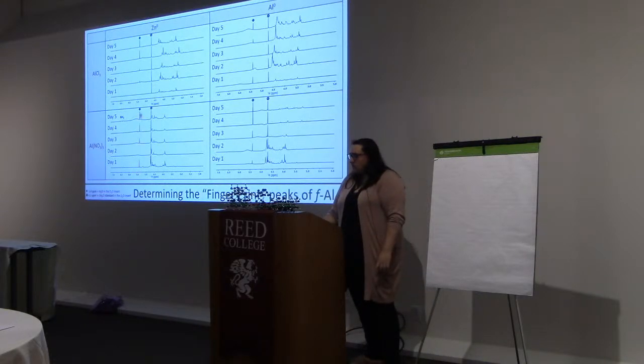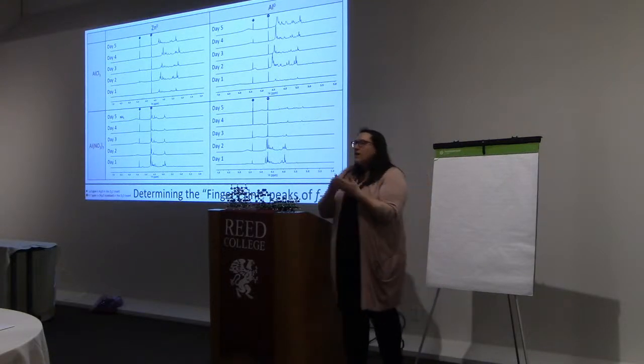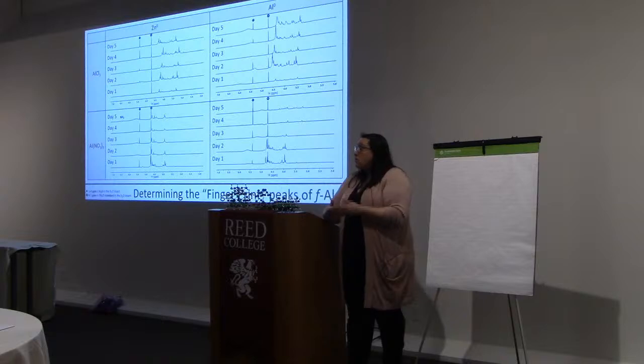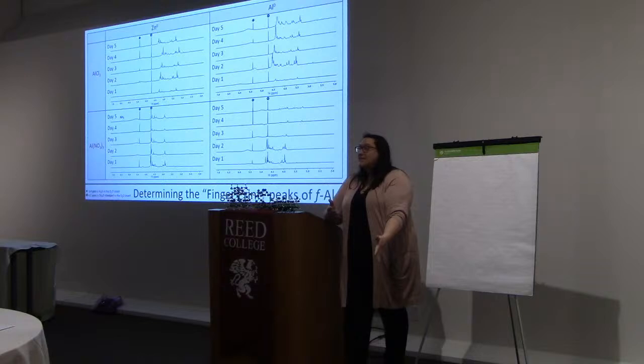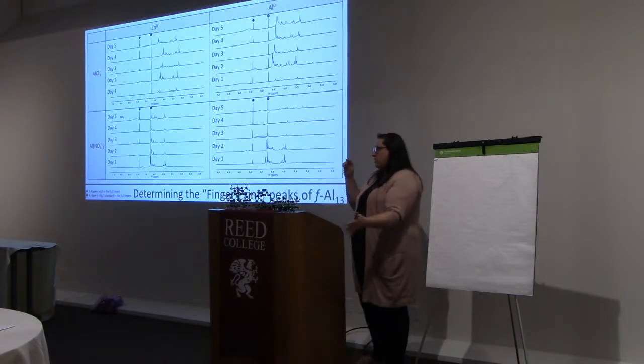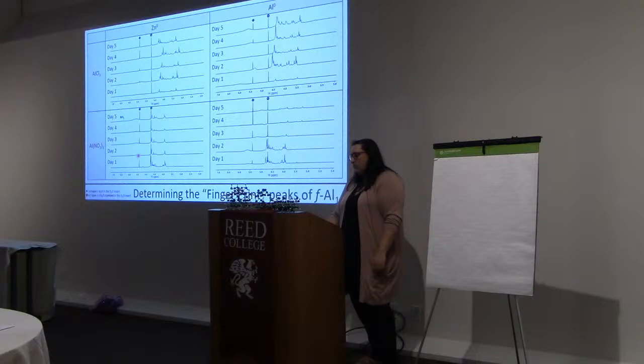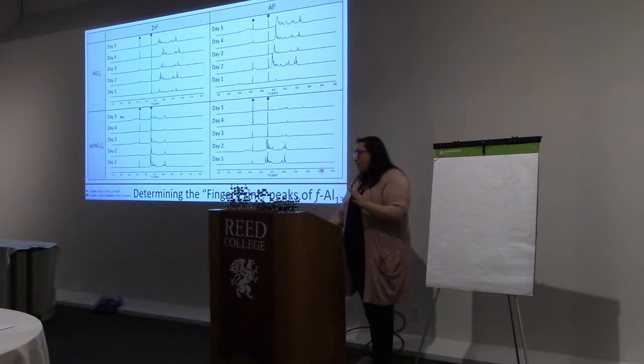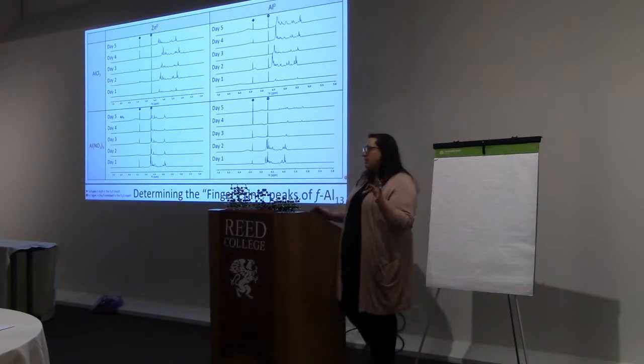There is a signal in each one of these that I put a little diamond by. Now, because we have a D2O insert, there's a little bit of water in our D2O insert, and depending on what the pH of our water that we're suppressing is, we don't always suppress the little bit of water in the insert. So that signal right there, we suppressed it because our signal was also on top of it. But those signals are water. We put a little reference in there, which unfortunately overlapped some of our signals in this one. And so we were able to normalize all of ours. And you see that as these syntheses happen, even right away for some of them, there's a mess. There's a ton of hydroxide bridges.